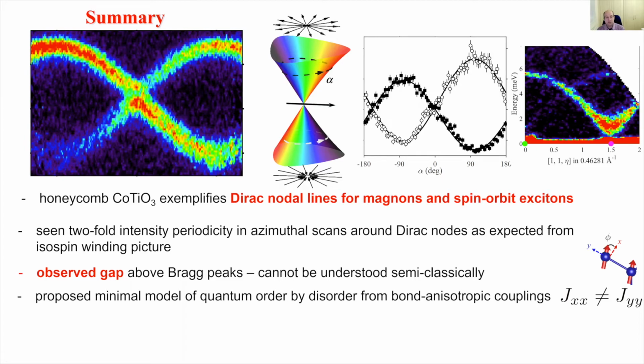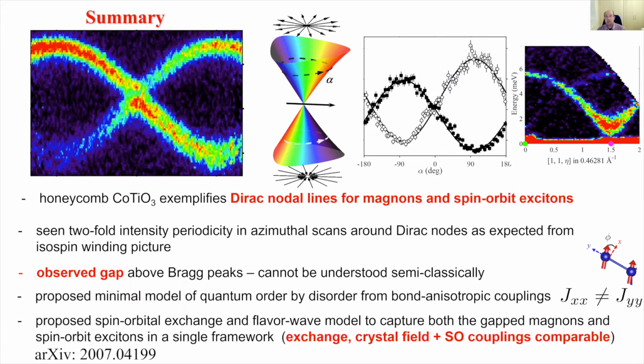Another possibility is that because in this system the magnetic exchange, spin-orbit coupling, and crystal field splitting are all of comparable magnitude, one has to treat on equal footing both the spin and the orbital degrees of freedom. So here, we've also found a mechanism for ground state selection in that the magnetic moments have both a spin and an orbital part, and then fluctuations of the orbital bit through virtual crystal field excitations can add an energy term that would select preferential directions in the plane as opposed to others.